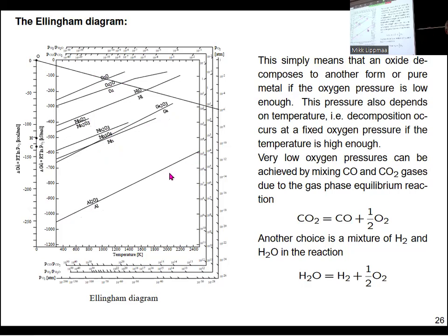So to reduce aluminum oxide to aluminum metal at, let's say, reasonable temperatures, so we are somewhere 1,300-400 degrees. So let's say somewhere here, the crossing point would be here. So if we draw the line from here, we would end up at oxygen partial pressures of like 10 to minus 20 atmospheres. Completely impossible in a practical sense.